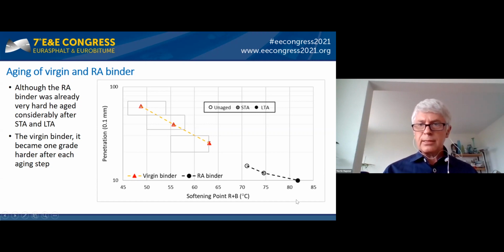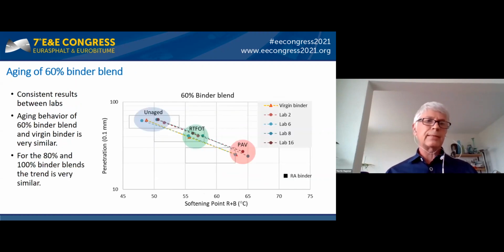What we also can see here is that the reclaimed asphalt binder, although it's even quite hard, it's still aging, not in the same amount as the virgin binder, but especially if you look at the softening point, ring and ball, it is aging about 10 degrees. So having that, all the labs were able to do their binder blends, aging them, testing them, and what I present here are only the results from the softening point, ring and ball, and penetration, because we don't have time for more.